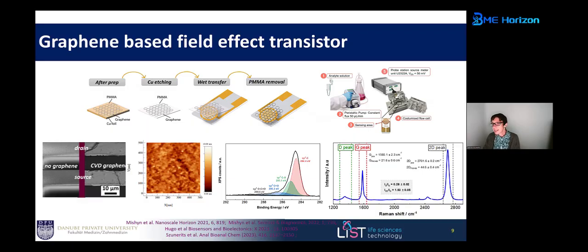You can partially validate this with Raman spectroscopy. In the Raman spectrum you see here, you definitely have a very nice G band, but you have a small contribution of the D band, which is due to the transfer of your graphene onto your interface and is linked to strain. What you probably don't see so well is eventual impurities of this PMMA residue, which you could see from XPS. But also, if there's only some percentage, you might not know which part of the oxygen functions on your graphene comes from the removal.